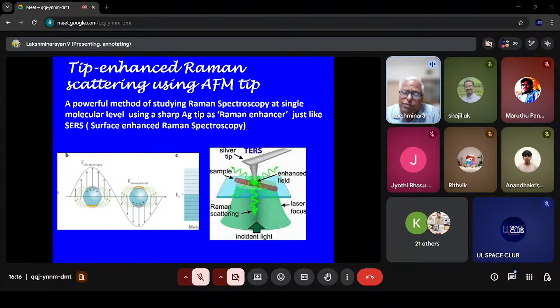The localized surface plasmon enhancement, in turn, actually enhances the Raman signal, both the incident Raman and also the scattered Raman. So if you have nanoparticles, these are the surface plasmons which are created. With the enhanced field, you can actually address the tip onto a single molecule also. For a single molecule, you cannot get a Raman signal in a classical way, impossible. But when you address it this way, you will be able to get a Raman signal at that point, with the signal enhanced by more than 1 million. So that way, you can get Raman signals of individual molecules.